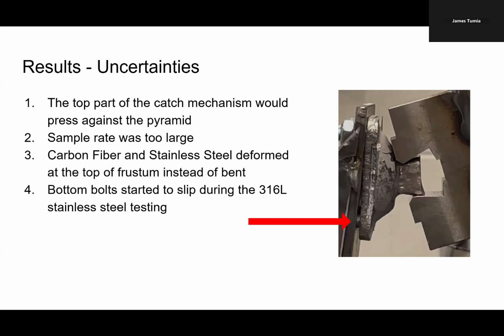Also, our sample rate was way too high, especially during the stainless steel test. We ended up with an overwhelming amount of data, which made analysis more complicated and introduced noise we didn't really need. The machine would sometimes randomly stop mid-test, saying it had run out of room for data. So we had to pause and restart tests, which led to gaps and some lost data.